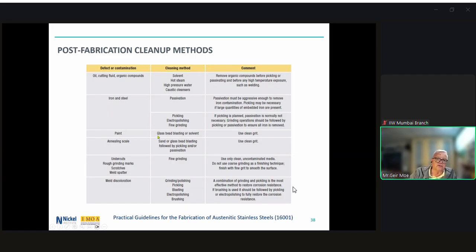For paint, you could remove it by glass bead blasting or a solvent. Annealing scale, you could use an abrasive method to remove a lot of it, followed by pickling and/or passivation. And so we can just basically say there are many different ways to achieve your post-fabrication cleanup, and this table summarizes many of those processes, and you can find that in the publication.